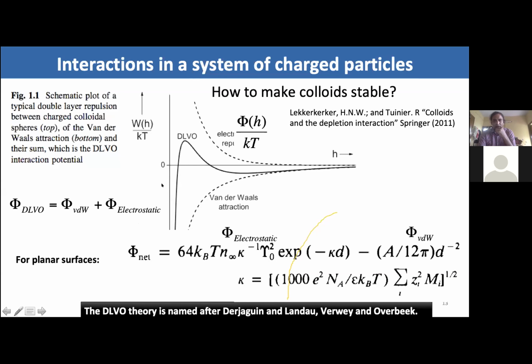What is plotted here is the potential as a function of separation distance between the particles. This is the van der Waals attraction term, the dashed line above zero is the electrostatic repulsion, and the sum of the two gives you the total DLVO potential. Because these two forces are opposing in nature, a maximum comes about, and this maximum tells us whether the dispersions in the fluid are stable or not. If the height of this barrier is very large, typically several tens of kBT, such colloids exhibit very good stability.